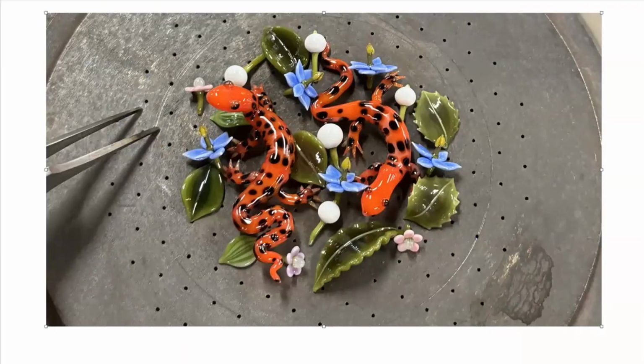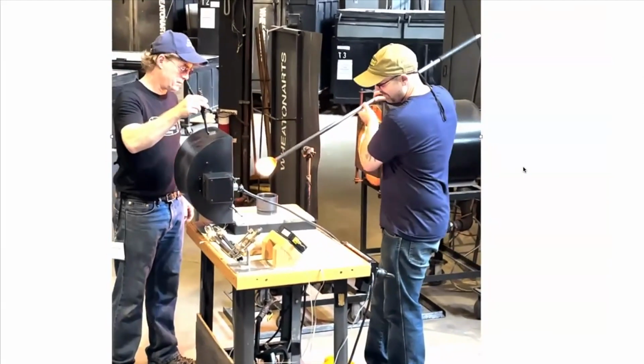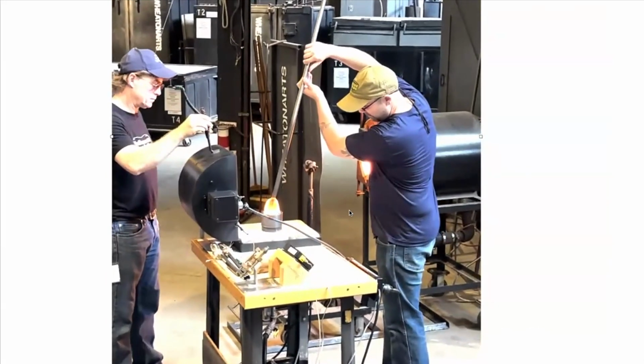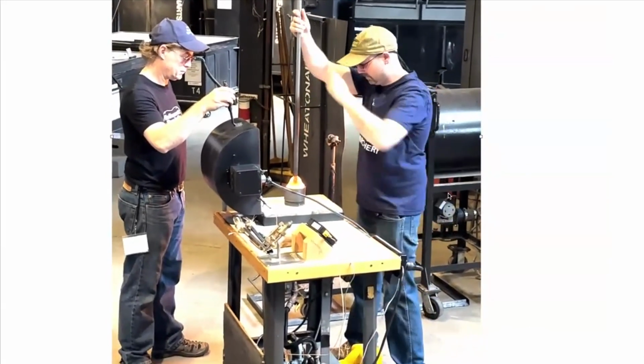Once they're getting ready to actually make a paperweight, they'll assemble the setup, they call it, on a hot plate like the one seen here. Notice there are these little holes on the hot plate. This is attached to a vacuum system on the underside so that when they get ready to encase the paperweight, they'll come through with a gather of glass and the setup is at the bottom of the steel collar that we see here in the middle of the screen.